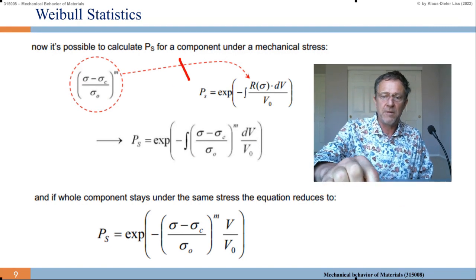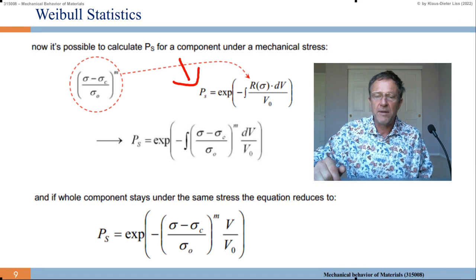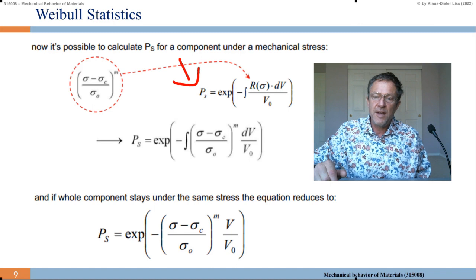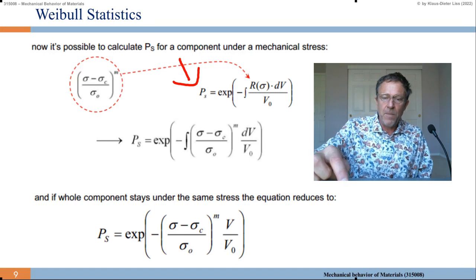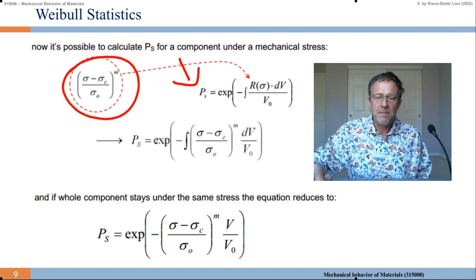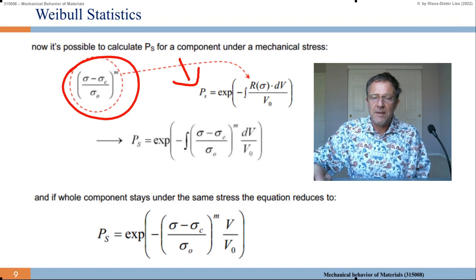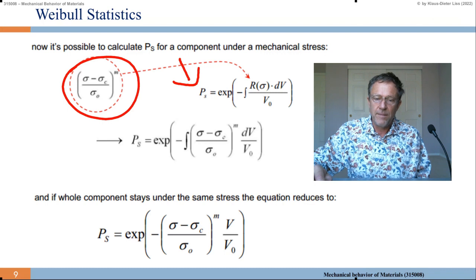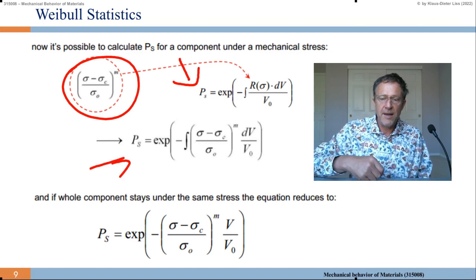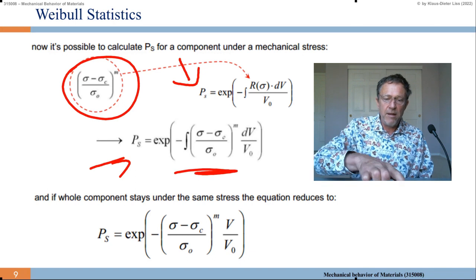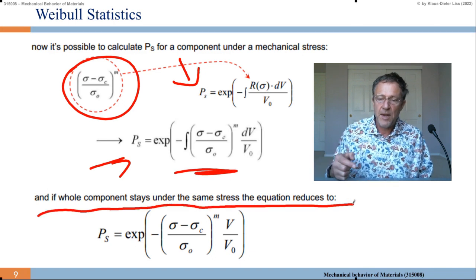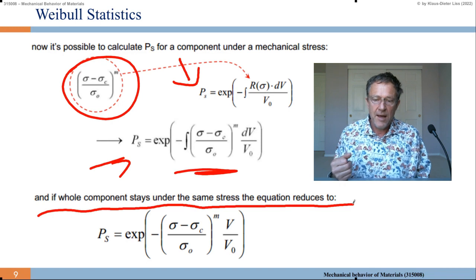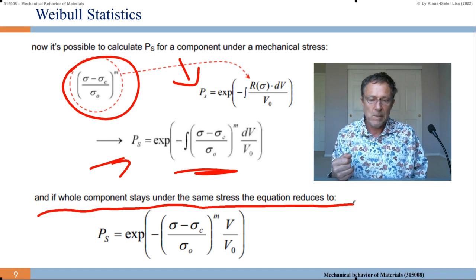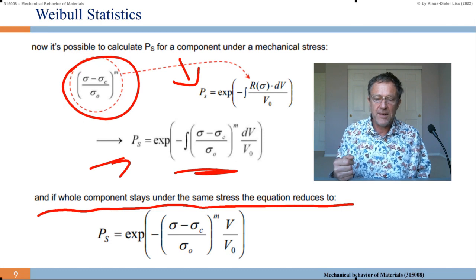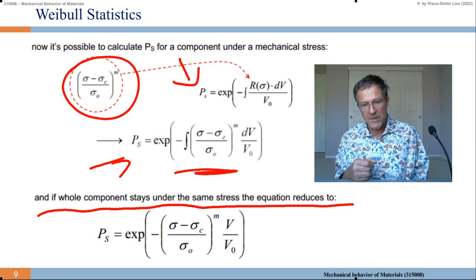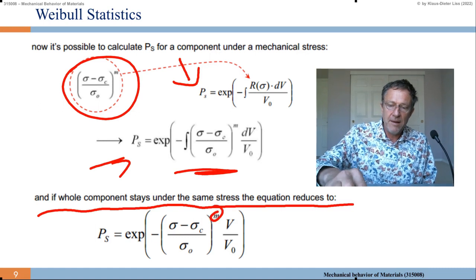Namely, we have the P for survival, probability of survival, equals exponential of minus the integral of R of sigma, for which we put in sigma minus sigma c over sigma 0, times dV over V0. And that leads to, here we put it in, to that equation. And if the whole component stays under the same stress, the equation reduces, we remove the integral, and the dV over V0 becomes V over V0. So PS equals exponential minus sigma minus sigma c over sigma 0 to the m, all in the exponent, times V over V0.